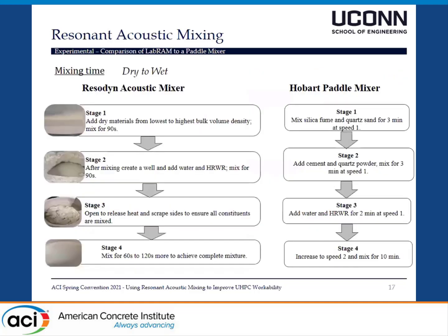And so this is what we found. These are the two mixing regimes that were employed with Resonant versus the Hobart paddle mixer. We can see that the average mixing time for the Resonant Acoustic Mixing was about 5 minutes, while for the Hobart paddle mixer, it was about 18 minutes, so 3.5 times greater than the Resonant mixer. So yes, Resonant Acoustic Mixing (RAM) can mix UHPC pretty quickly.